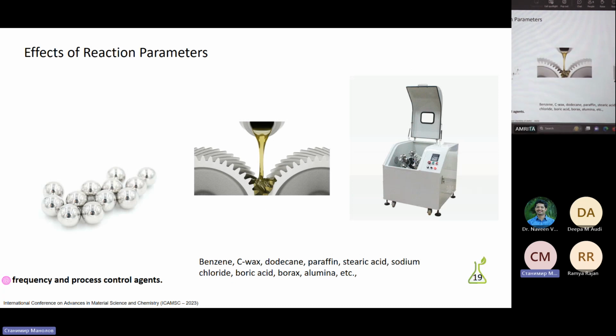The lubricants and surfactants can be utilized as process control agents to minimize the effect of cold welding between powders and prevent agglomeration. When the surfactants absorb on the particle surfaces, they interfere with cold welding, and the surface tension decreases. Benzene, C-wax, dodecane, paraffin, stearic acid, sodium chloride, boric acid, borax, alumina, etc., have been widely used as process control agents, and during the milling process, they decompose and interact with powder particles and produce compounds. The process control agents directly influence the final phase, the solid solubility and contamination levels, and the glass forming range.